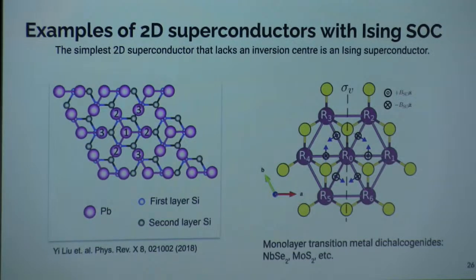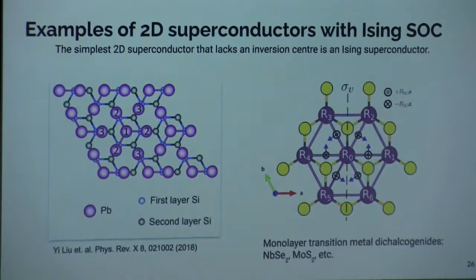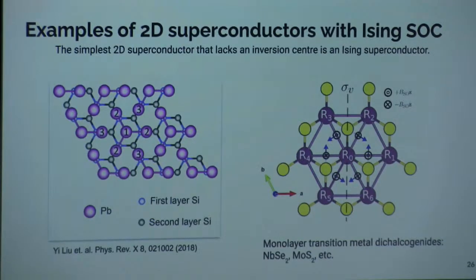Perhaps the most famous non-centrosymmetric superconductor is the Rashba superconductor. You take a 2D superconductor, put it on a substrate, which induces Rashba spin-orbit coupling. But Rashba has two components. Ising superconductors only have one Z component, and this is why they are the simplest superconductors lacking the inversion center. You can get an Ising superconductor by putting, for example, a lead monolayer on a silicon substrate, or intrinsically in monolayer TMDs. And here I will talk about the hexagonal TMDs. Everything I'm about to show applies to all of them, but I will use niobium diselenide as the working example.